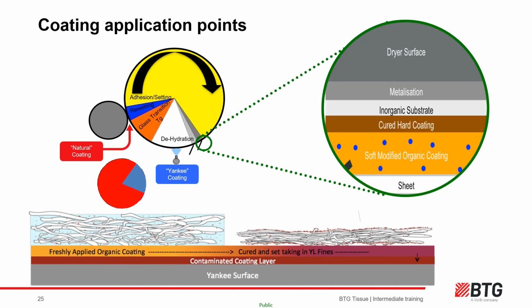If we dig deeper into what happens at the creping blade, we see the layers again, the dryer surface, the metallization, inorganic substrate, and then what we are really interested in on a daily, if not hourly basis, the hard cured coating layer and the more freshly applied organic coating layer.